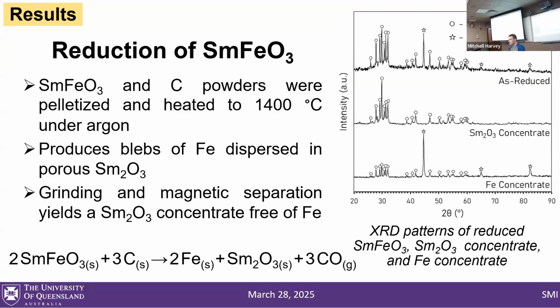This is X-ray diffraction again. Each of these peaks are labeled with what phase they represent. So this top line is the as-reduced sample. We've got peaks for both the samarium oxide and iron metal.